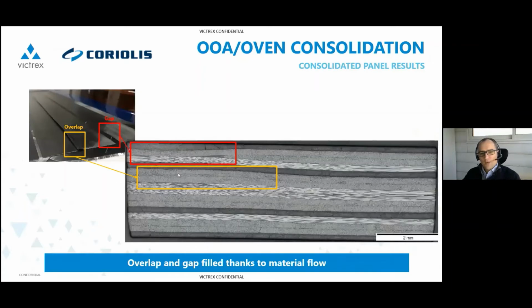And again, I'm not an expert, but that's what we understand. For the AFP process, the overlap between two courses or some gaps could be a challenge sometimes. But here, thanks to the flow of the resin, even if you have, let's say, defects during the layup process, once you consolidate the laminate, you get rid of them. So it is getting very even, and you don't see them anymore. So it seems to be quite unique, and that helped a lot the processing step. So at the end of the day, that helped a lot making the part. So that's a pretty significant input here.